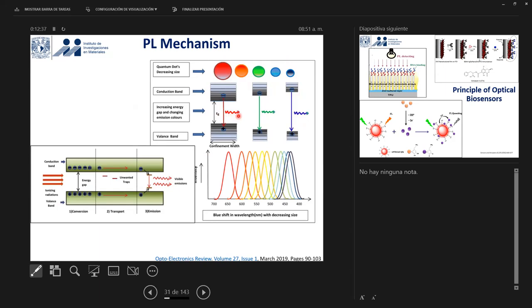a red color. So the aim is to control the size of nanoparticles or nanowires, the diameter of nanowires, to attain the quantum confinement effect. And finally, we can control the band gap of these materials and we can control the emission. The same material can emit in different colors. So that is the thing of photoluminescence, how it works.